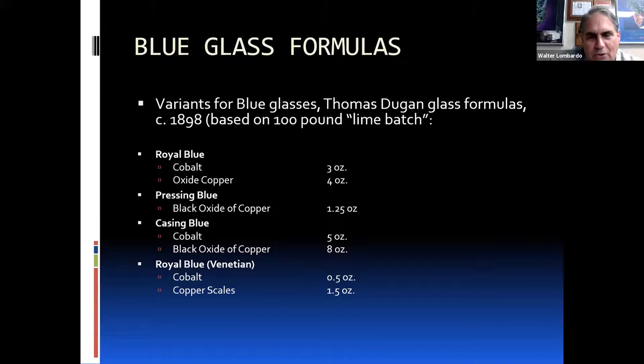So to make a royal blue, for every 100 pounds of the batch or the basic glass mixture, you needed 3 ounces of cobalt and 4 ounces of copper oxide. That's 7 ounces out of 100 pounds. That's a pretty small percentage, and you get a royal blue out of that. If you have what's called a pressing blue, which is a light blue that was used in what they made press glass, it is a black oxide of copper. That's the mineral tenorite. And you use only 1.25 ounces per 100 pounds.